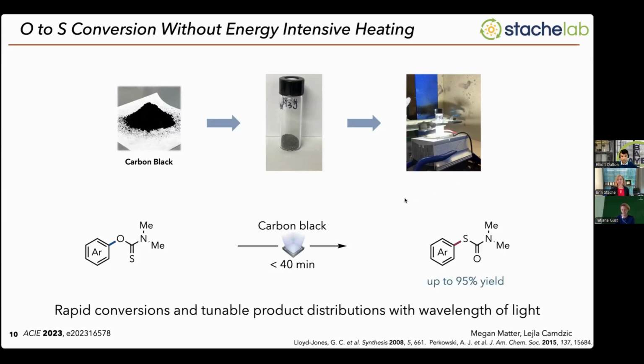And then simply by the end, she can just filter off the carbon black and get the product in up to quantitative yield. And so this works across the entire substitution pattern that has been explored for Newman-Kwart rearrangements. Even very high activation barriers proceed with really good yields and efficiencies. And we can actually tune some of the product distributions by changing the wavelength of light. So a very simple procedure, solid state chemistry, essentially mixing carbon black with a substrate, irradiation, and then you can filter off to get the product.